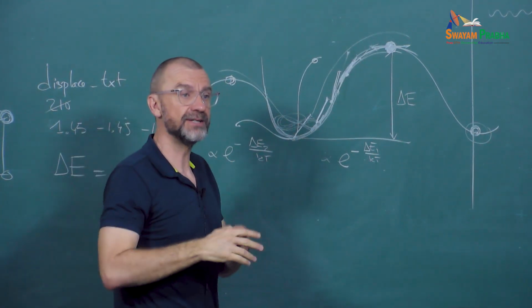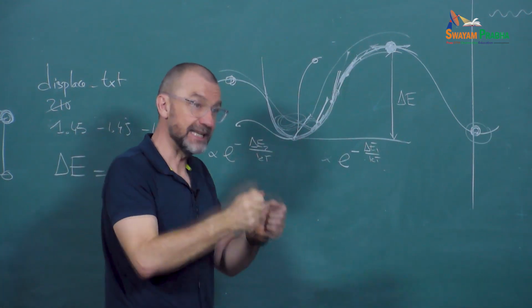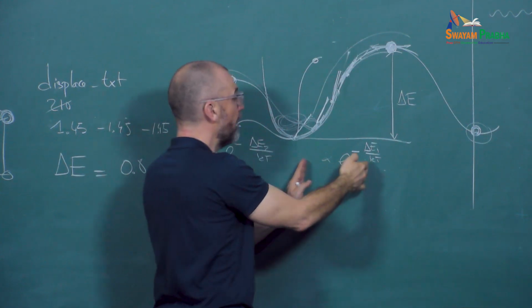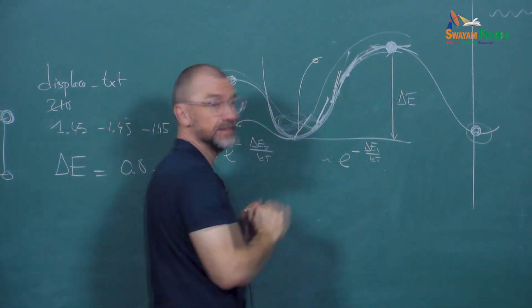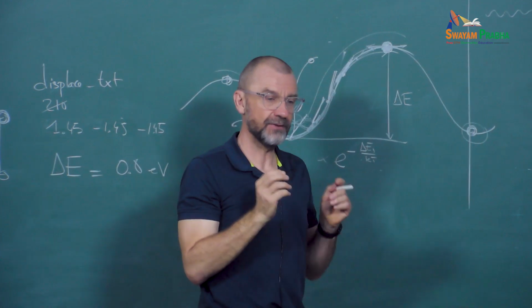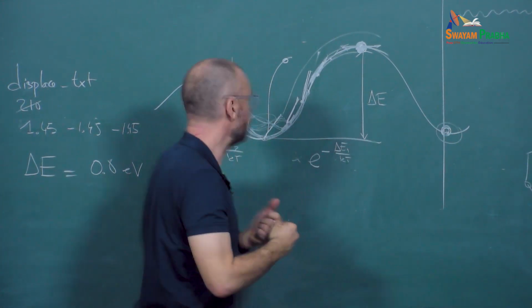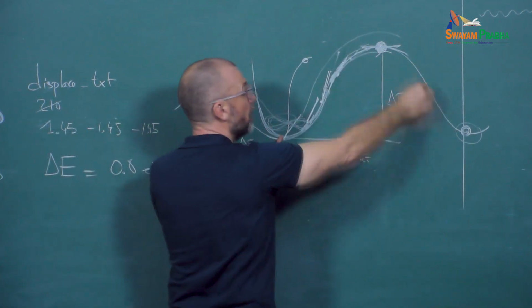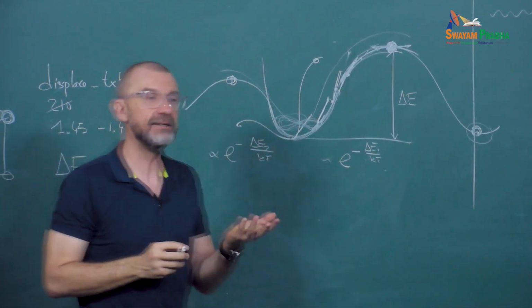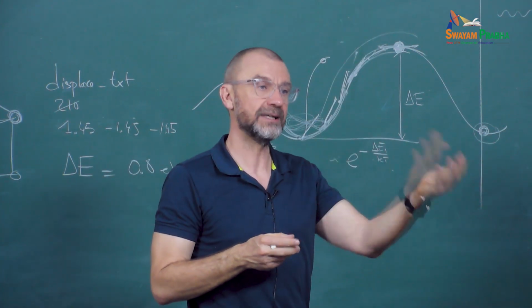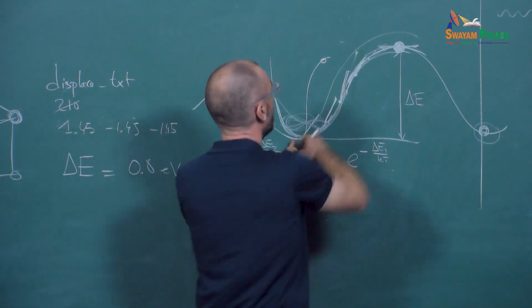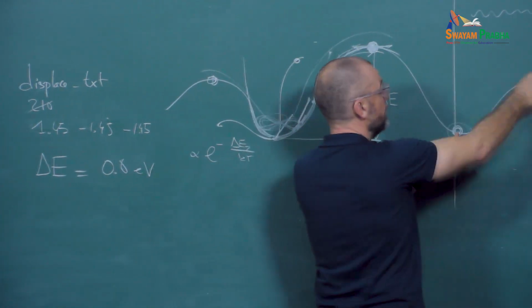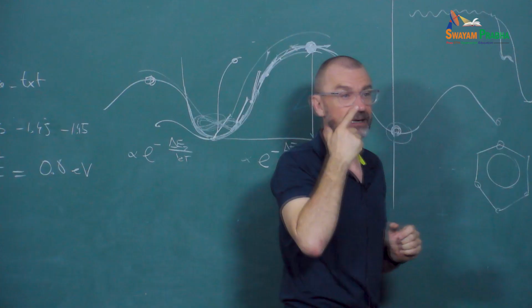Kinetic Monte Carlo is a way to select which of the two the system will go above and how long it's going to take to go above this barrier. So it allows you to have a physical time. You no longer model all the vibrations as you do in MD. You only go above the energy barriers, and kinetic Monte Carlo will give you the characteristic time scale that it would take to go above this barrier, and then when you are here, you do it again. And then here, and then you do it again and again and again.